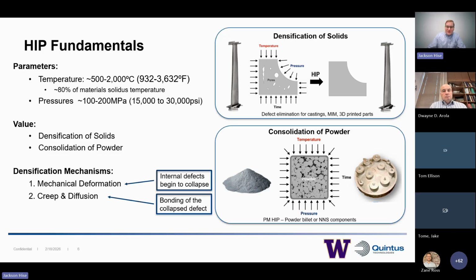Here we're applying our temperature and pressure around our part, and given that there's a gas-tight surface, we're able to decrease that porosity and fully densify our material. We also see a growing interest in the consolidation of powder, where we create a can, a near net shaped can to the component we want to create. Then we fill it with powder, pulling a vacuum on this and then placing it within the HIP. We can get a single uniform piece of material.